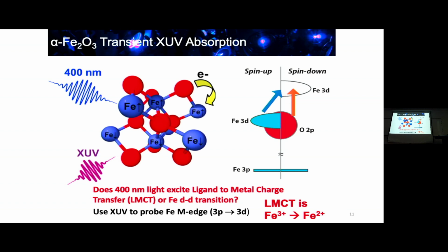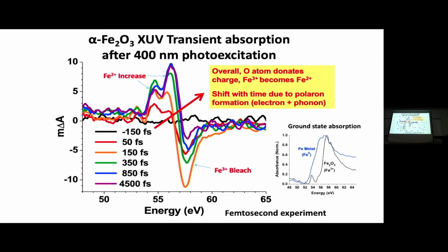So these two are very distinctly different. If the oxygen transfers an electron, then the iron changes from iron 3 plus to iron 2 plus. But if it's a D to D transition, the iron is still in its same charge state. So we would be able to distinguish these if we could see the charge state of the ion. So we could do that experiment.